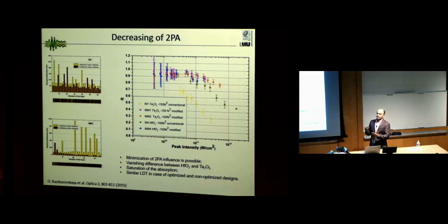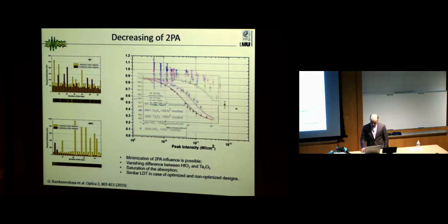We can work with these mirrors at much higher intensity, and you can see the mirrors with tantalum, which provide minus 100 femtoseconds squared delay, shown with violet color. If you compare with the curve for yellow color, you see that it's postponed to much higher intensity. And with these mirrors, we can work with at least 10 times higher intensity than with the original mirrors.